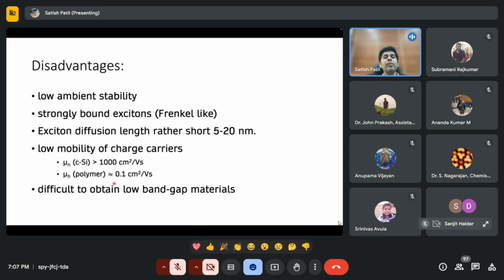They are also difficult to obtain as very low band gap materials. Silicon band gap is 1.1 eV. When you shrink the band gap of a polymer, you make the HOMO and LUMO energy levels smaller and smaller, making polymer semiconductors less than 1 electron volt. These materials will undergo some side reactions. For example, it is very easy to oxidize a low band gap polymer because you are changing the ionization potential and electron affinity of these materials. So it's difficult to obtain low band gap materials.